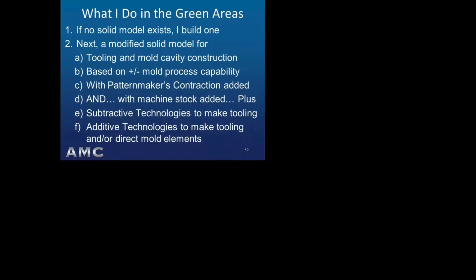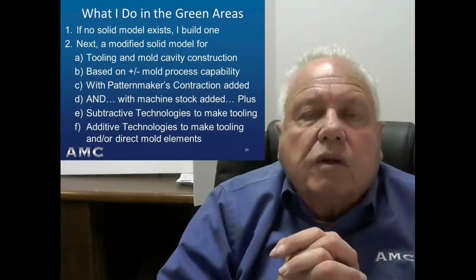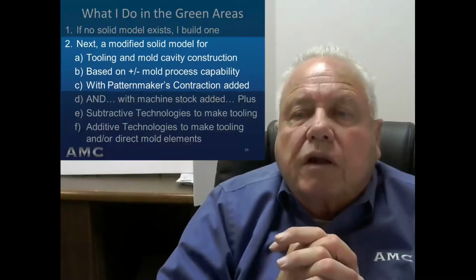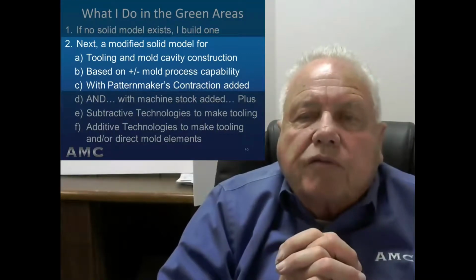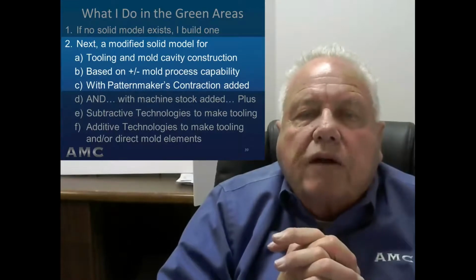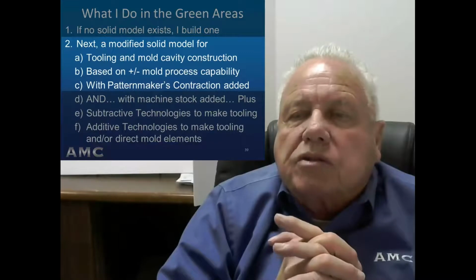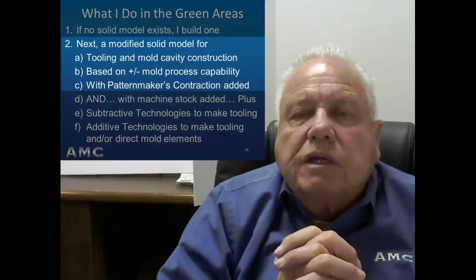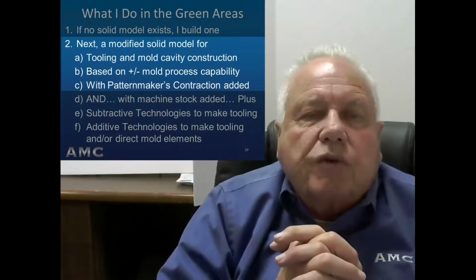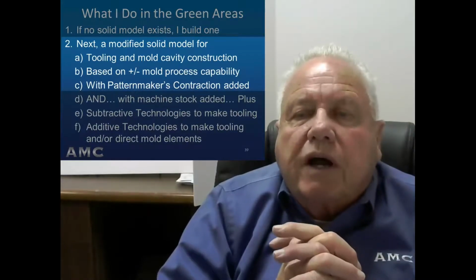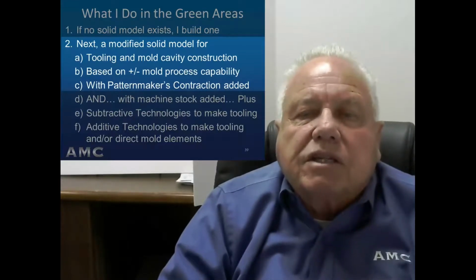Whether I wind up being turnkey source or the technical lead as a collaborating partner in a metal casting supply team, here's what I do in those green areas of the manufacturing engineering collaboration graphic. If no solid model exists, we build a solid model of the as-cast and or finished casting from the 2D drawing. Based on the manufacturing engineering collaboration with the metal caster and the machine shop, we build a modified solid model that adds the mold parting planes, mold draft, core to mold match lines, core print to mold match lines, core and core print drafts, chill prints and chill print draft, and connection surfaces for the in-gates, risers, and vents.